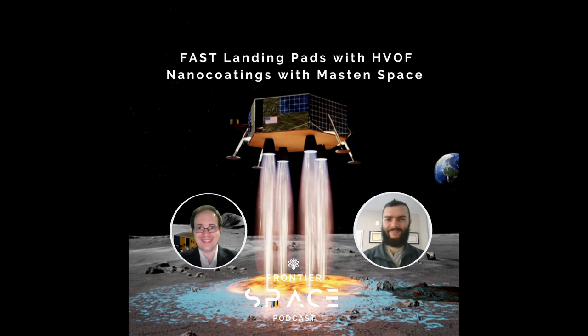The depth of injected contaminants that you would get from a rocket exhaust plume varies greatly by the size of the rocket. If you get a rocket firing close to the surface, you can get what's called a deep cratering effect to form. You can create a crater as deep as the rocket plume in roughly 0.4 of a second. Something the size of an Apollo engine could get down to a meter pretty quick if it were firing a little closer to the surface.